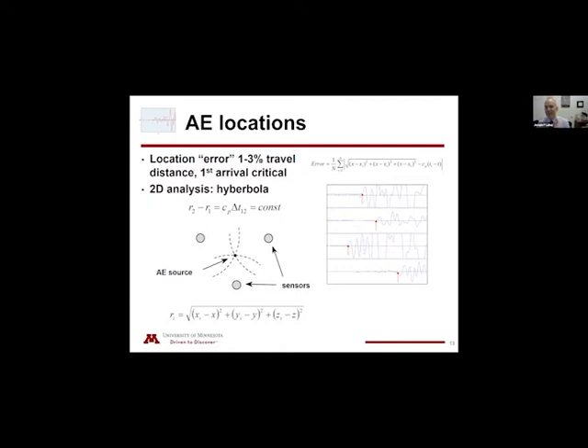I should make the comment that this is a very good signal in the sense that if we look at the nature of the signal prior to the event arriving at the sensor, this is a very low noise. So the signal to noise ratio here is very good. I could show that this is not as good, but still I would say very good. There are signals, and picking out the P wave is quite difficult. The other thing I'll mention is that typically we'll allow the resolution of our measurement to clip the time history. So it may be that the threshold for recording is at this level of amplitude because of the pre-trigger feature of the data acquisition system. We're able to record the time history prior to that threshold.